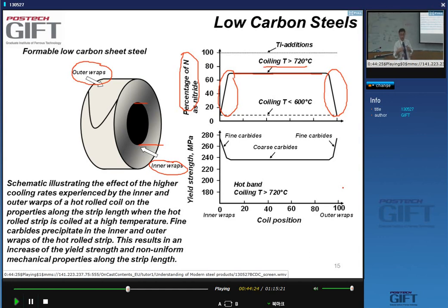Because the cooling rates are much higher at the inner and the outer wraps, we get a much different microstructure at the start and the end of the coils, and so you get fine carbides or fine pearlitic islands in the microstructure, and as a consequence, the strength of the steel at the start and at the end of the strip is much higher than in the rest of the strip. Yes? So you're basically making a product that does not have homogeneous properties. And you can see it's not a little bit. You know, it's 40 megapascal.